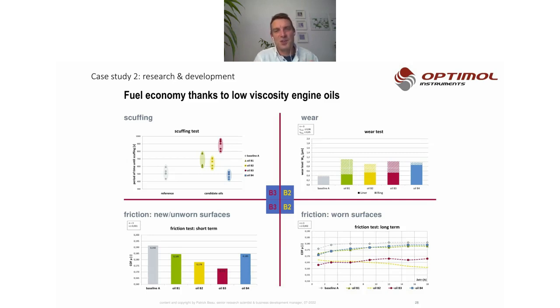So it was a short-term test with fresh oil and fresh parts, and it's shown on the left side. Let's say the initial friction situation. As you can see here, all those solutions do decrease the friction, but as you remember, they will increase the wear. And you are able to run those test rigs overnight for long-term tests.